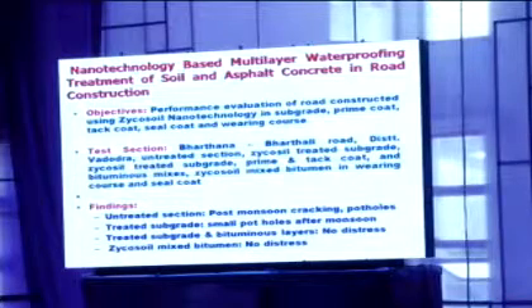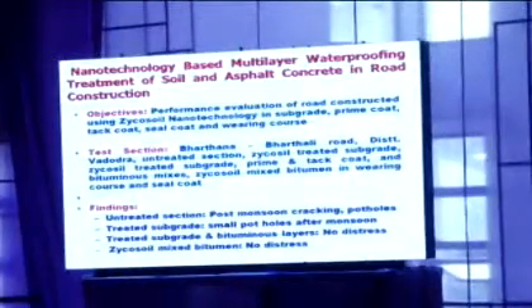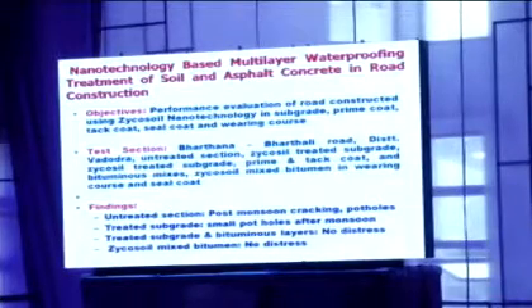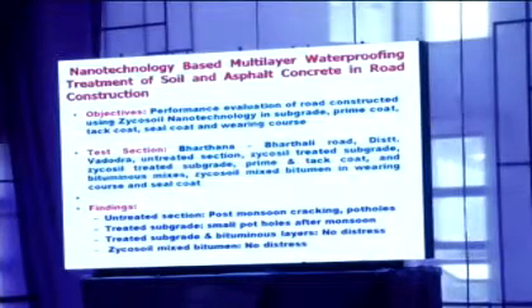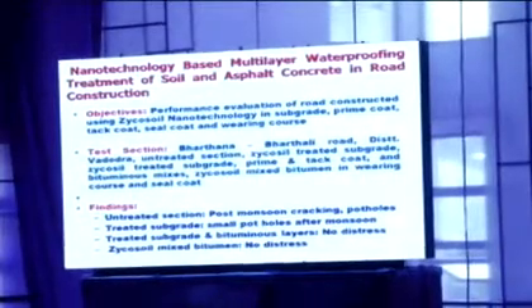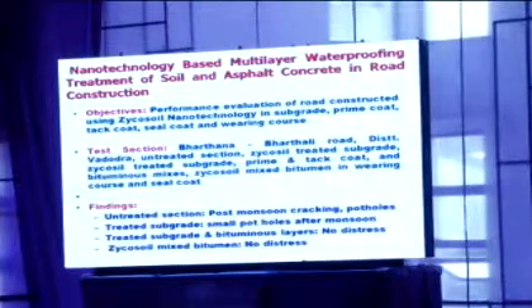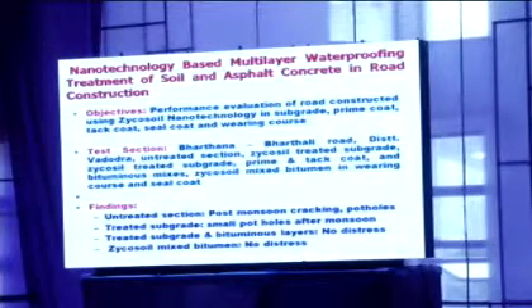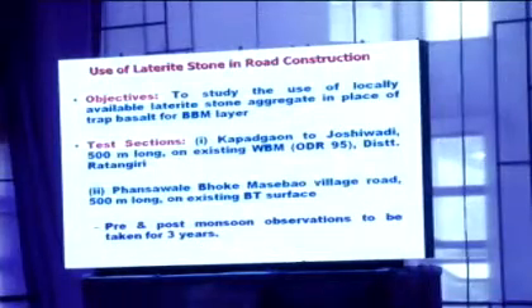It has been observed that in the untreated section, where there was no Zycosil, post-monsoon cracking and potholes were observed. But in the section where Zycosil was used only in the subgrade, small potholes were observed after monsoons. But when Zycosil was used in all the layers, there was no distress on those test sections. That means Zycosil is proved to be a wonderful material, as the findings of these projects have suggested.